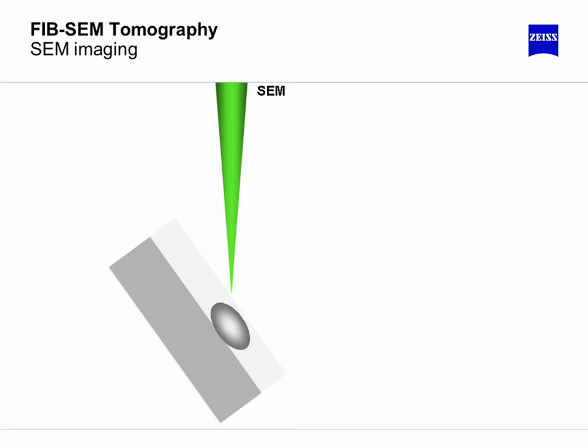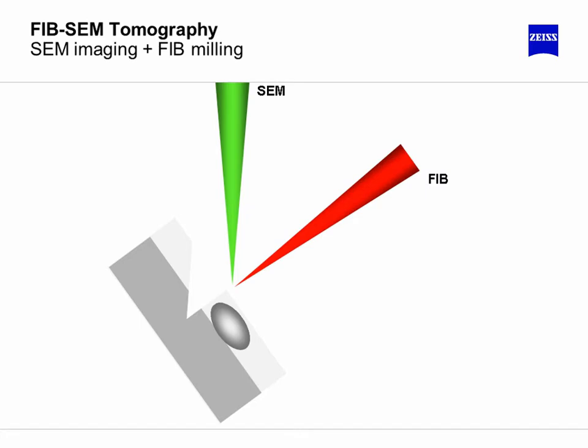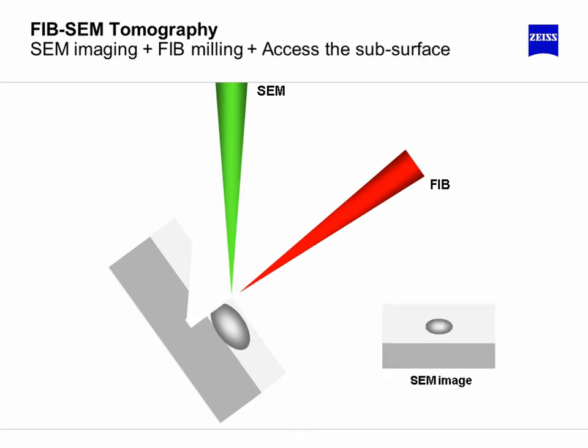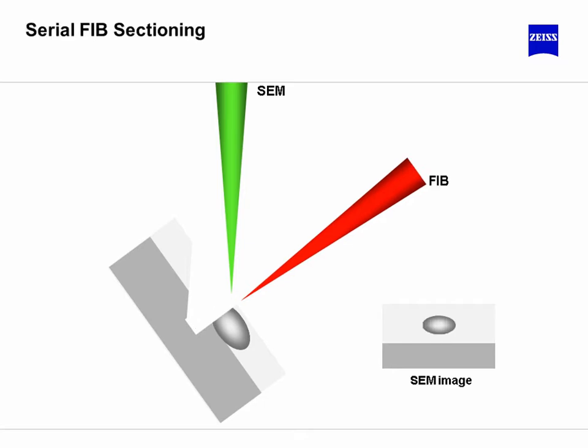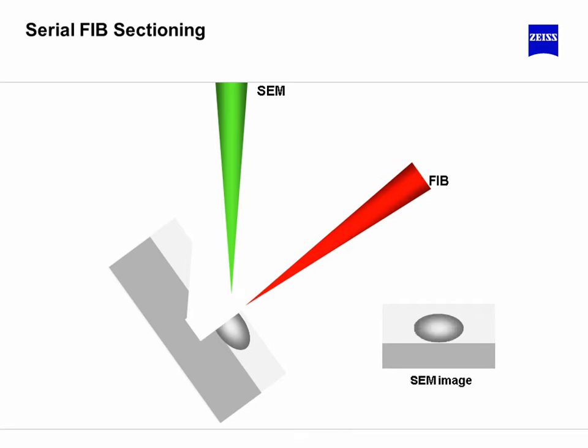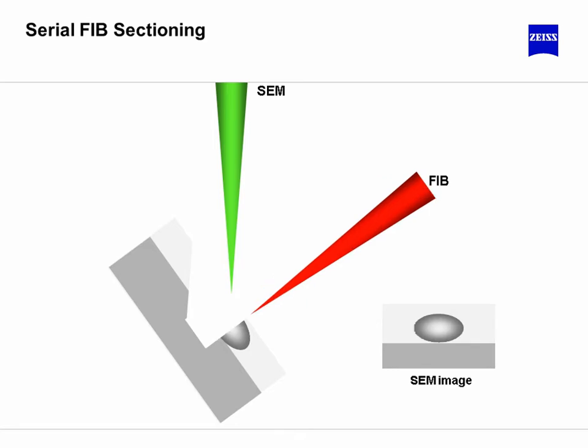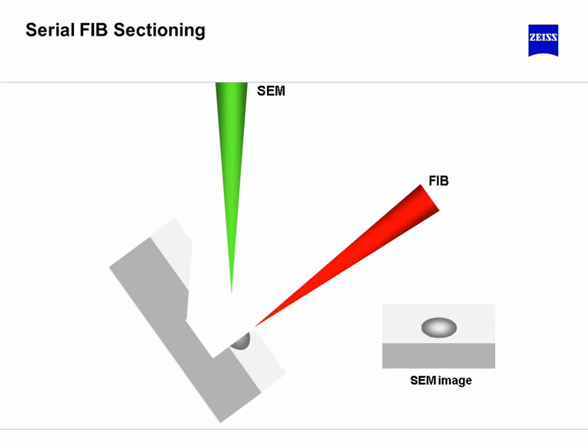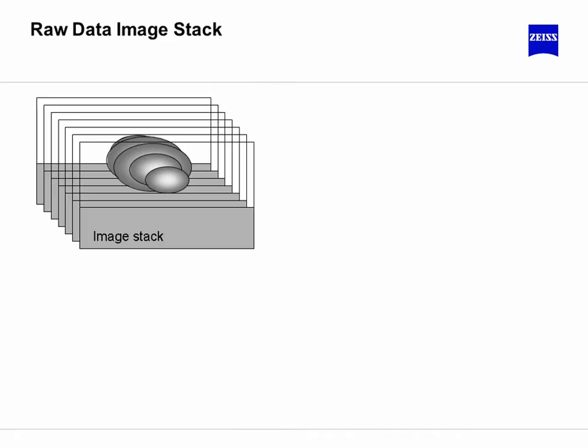Once you have found the region of interest, the sample is tilted towards the FIB column. Then a trench is machined into the sample so that the area or volume of interest is accessible by the SEM beam. And then you start slicing the sample using the focused ion beam and acquiring images with the SEM, as you can see here. This process is iterated a number of times. Typically, a FIB-SEM tomography run has 100 to thousands of images. And once this process is finished, you end up having a stack of images, as you can see here.